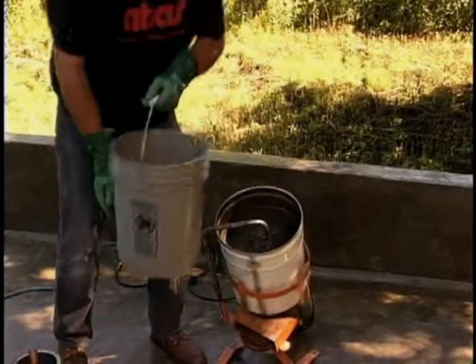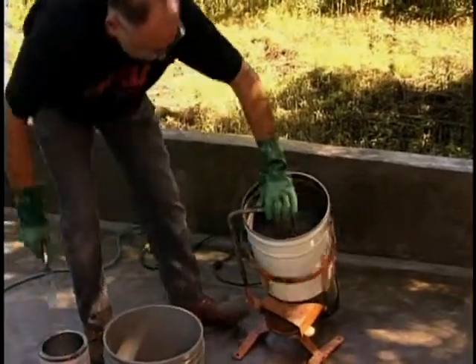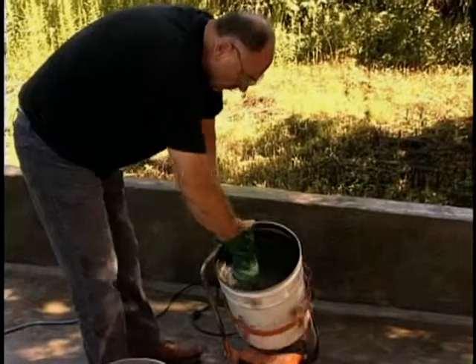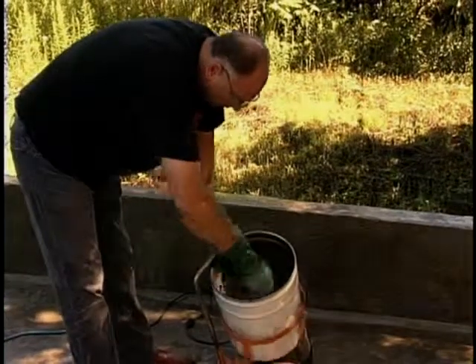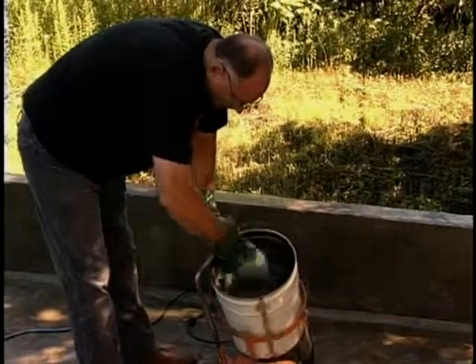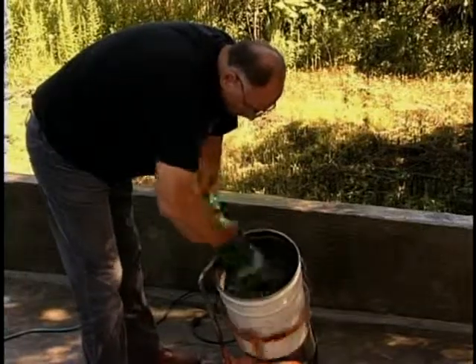For the first batch at startup, a small amount of powder left out of the mix will allow the hose to wet out properly. Subsequent batches, using the full amount of powder, will be slightly thicker.